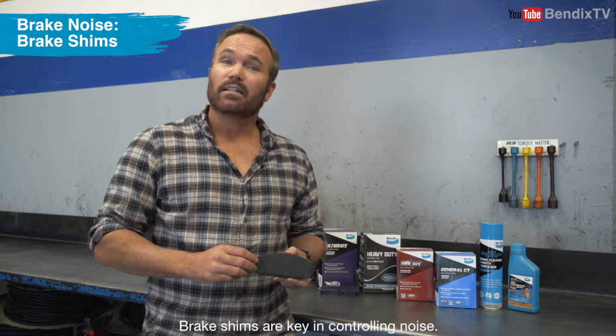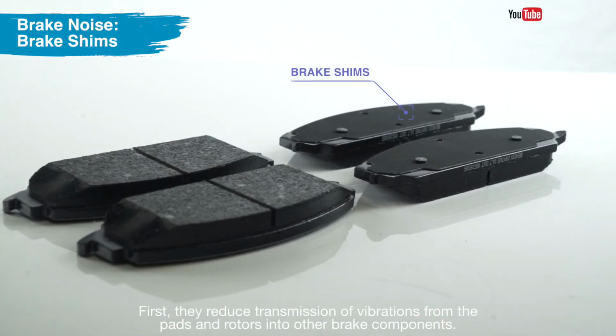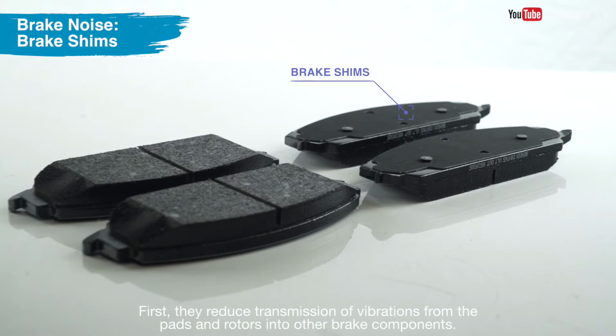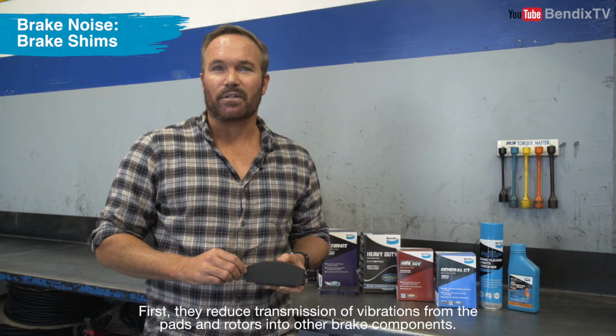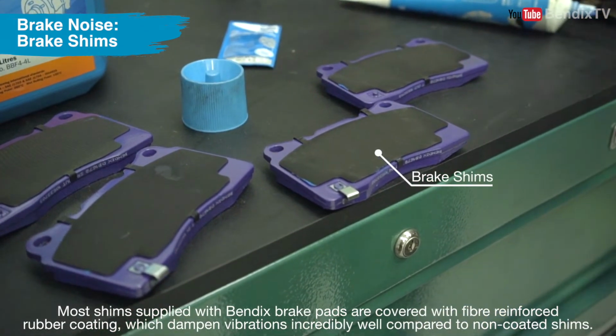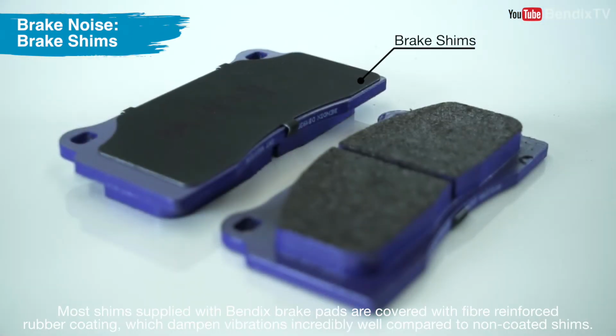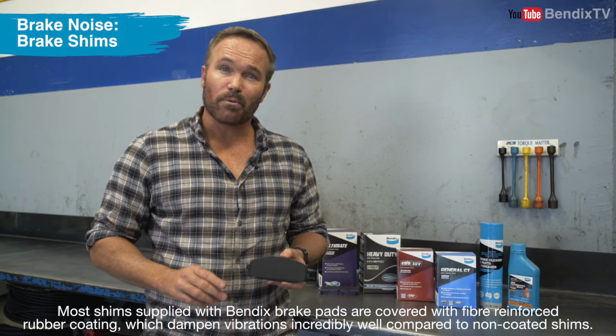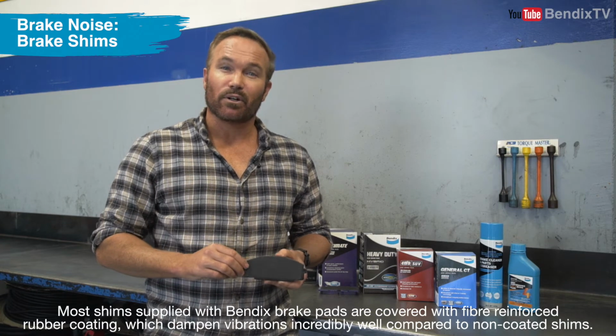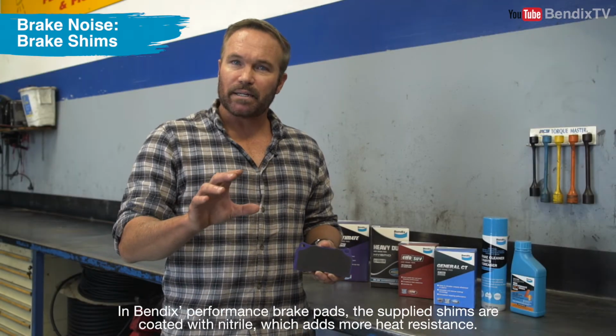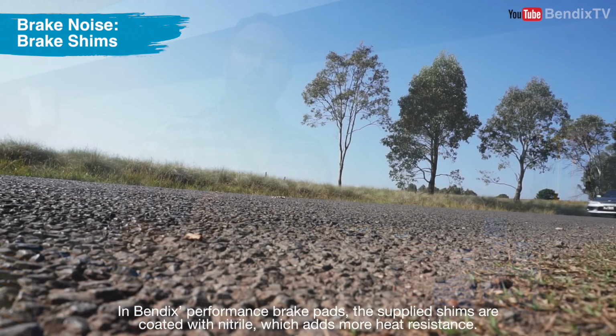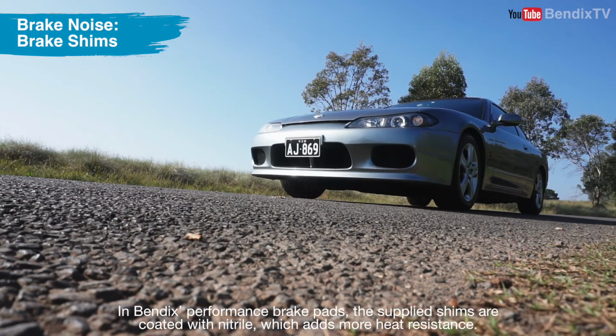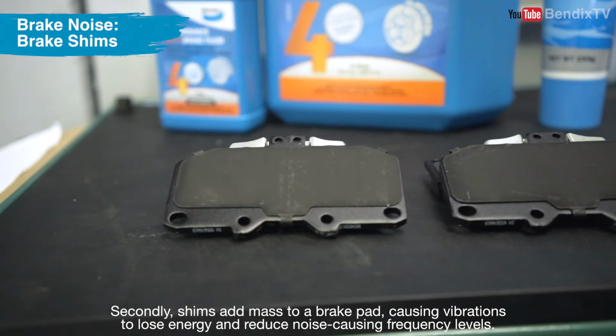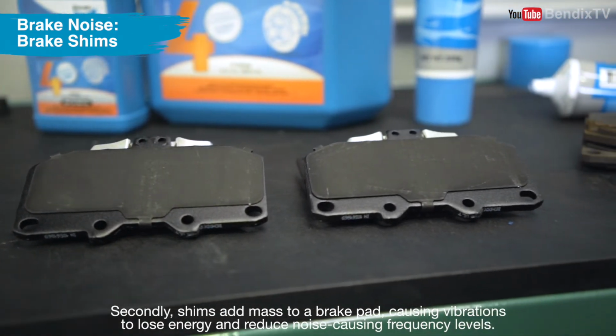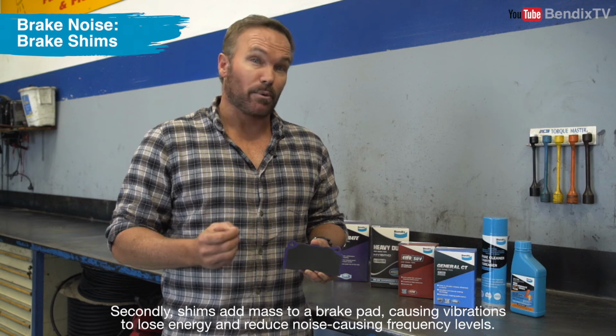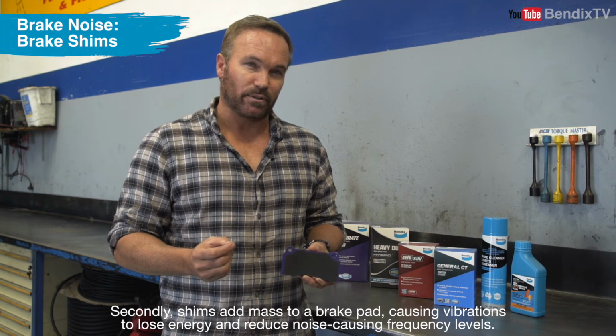Brake shims are key in controlling noise. First, they reduce transmission of vibrations from the pads and rotors into other brake components. Most shims supplied with Bendix brake pads are covered with a fibre reinforced rubber coating, which dampens vibrations incredibly well compared to non-coated shims. In Bendix Performance brake pads, the supplied shims are coated with nitrile, which adds more heat resistance. Secondly, shims add mass to a brake pad, causing vibrations to lose energy and reducing noise at certain frequency levels.